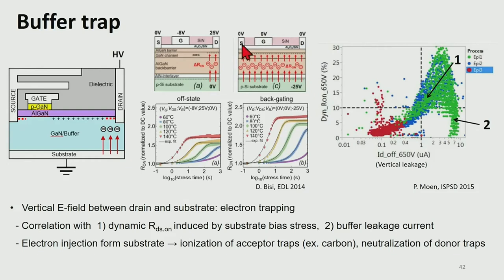But at the same time, since we apply low voltage on the top terminals, we can exclude the surface trapping mechanism that we reviewed in the previous slide. If you see the bottom figures, the dynamic RDS,on of the standard device shows a very similar temperature dependence to the backgating stress data. This indicates that the dominant trapping mechanism in this device is the electron trapping in the gallium nitride epi. To suppress this electron trapping in the epi, epi growth condition optimization is critical. For example, carbon level optimization is very critical for high quality epi design. And even at the same carbon level, other growth conditions, such as temperature or pressure, can affect the crystal quality.